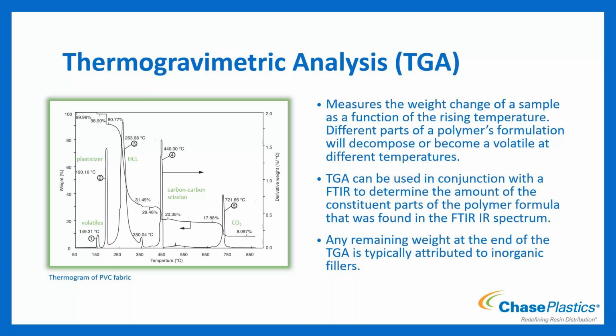It also can typically get to a little bit lower levels of telling what's in there than some of the other methods. So if it's something like the FTIR, generally it's kind of accepted, if you're under 1% of something, it's not going to show up. You have the potential of being able to see it with the TGA that you are not able to with the FTIR. So a great way to distinguish what's in it, and now tell me how much of it is in it.